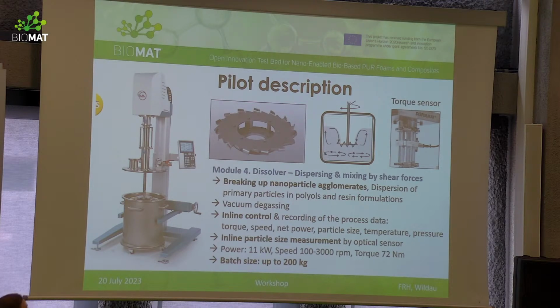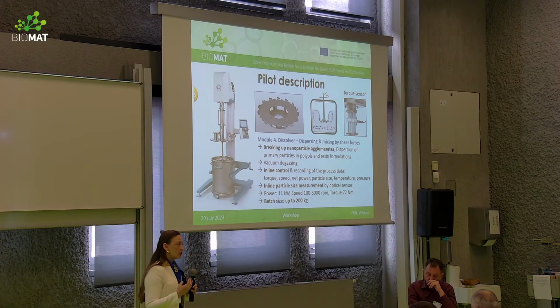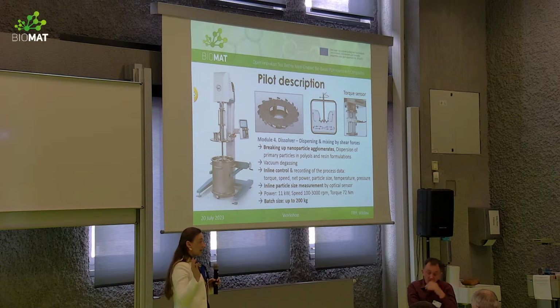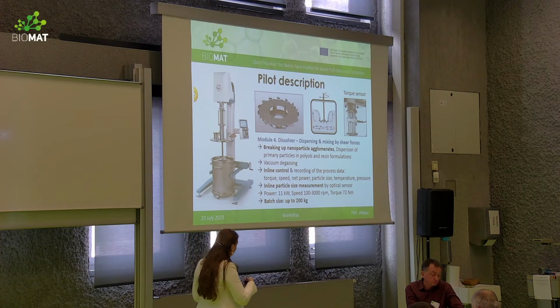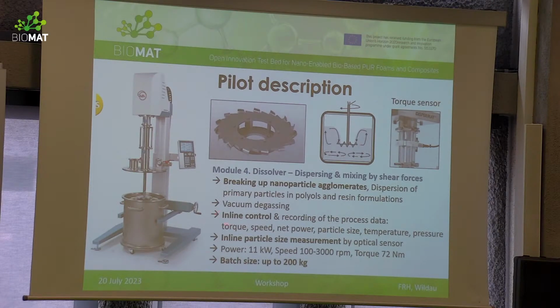Next plus in this case, we can make dispersing with vacuum degassing. Also, we can control temperature. It's not a secret. If you have strong shear forces, you have increasing of temperature, and in some cases it can be critical. This device allows cooling and heating during the mixing, and we can have stable temperature during the process. We have no other influences and artifacts. And we can also use inline controlling during the mixing process.